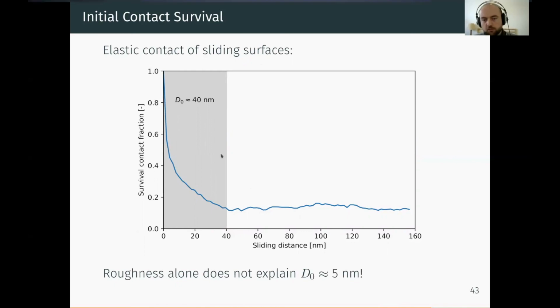So those simulations are purely elastic contact simulations that do not include those fatty acid molecules. And it's therefore apparent that roughness alone is not sufficient to explain what they observe in the experiment with this d0 of 5 nanometers, because we are an order of magnitude larger.